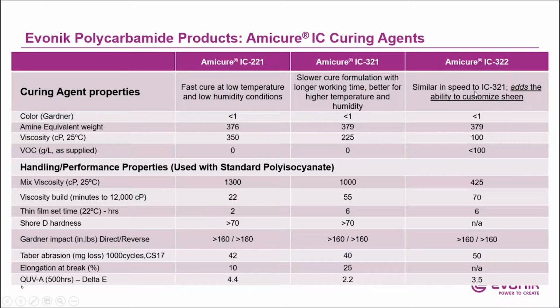And what we talk about here is, without matting agent, you get a nice high gloss finish. With the matting agent, you can get the down glossing, so you can get down to a satin finish. If you look at the curing agent properties of these three curing agents, they all have very low color. The amine equivalent weight is about 375 to 400. So what it does is allow for a 2-to-1 mix ratio with the polyisocyanate resin.